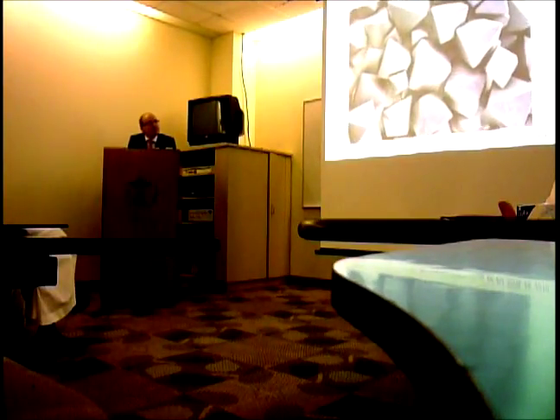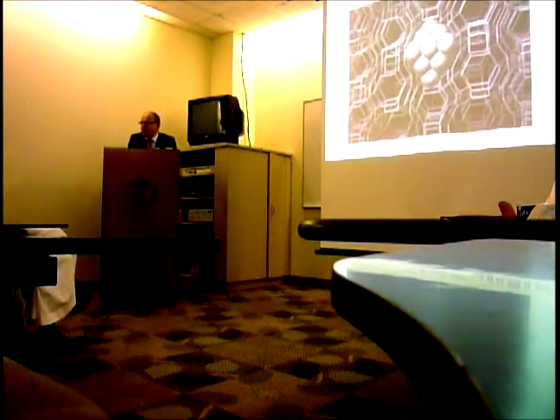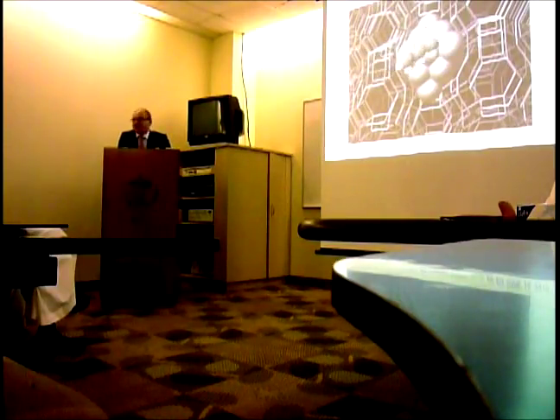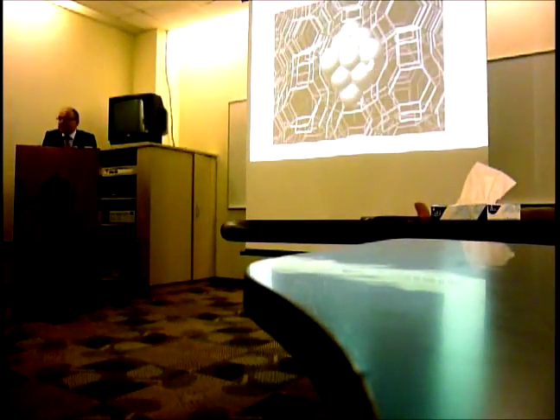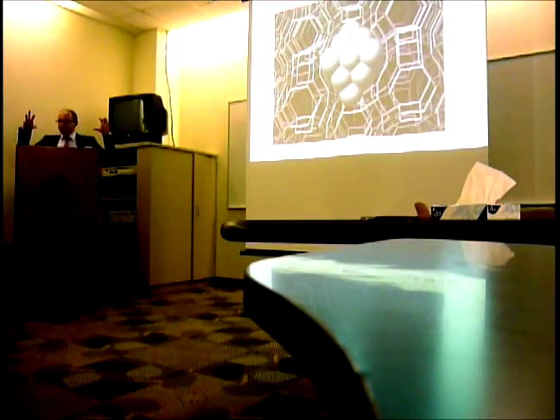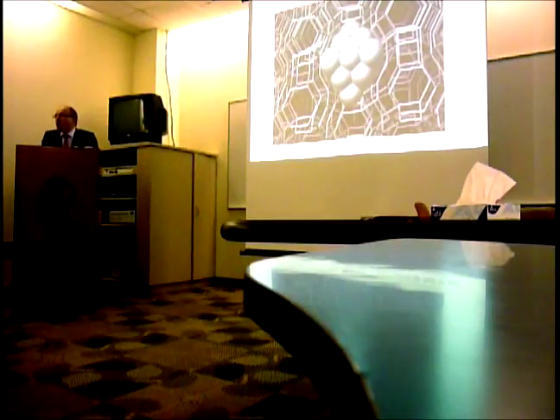These extrudates contain crystals, and these crystals contain nanopores, and within these nanopores you find balls, nanoparticles, in this case platinum, tin, and they can convert the propane to propylene and hydrogen. So what we'd like to do, as I showed you, like a bird zooming in, is go into the details and try to uncover what's going on at this active site.